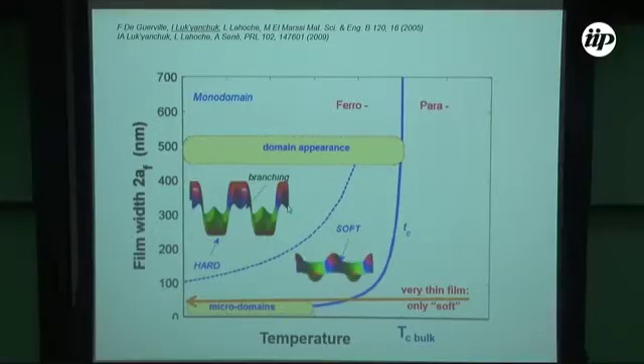So in soft domains, the polarization changes gradually, like a sinus-like profile, in both directions, across the film and in the film direction. Which is quite natural if you are looking near TC. But what is important is that because we have some scaling of the equation, in principle, soft domains should exist in the very thin films. The domains should be always soft.